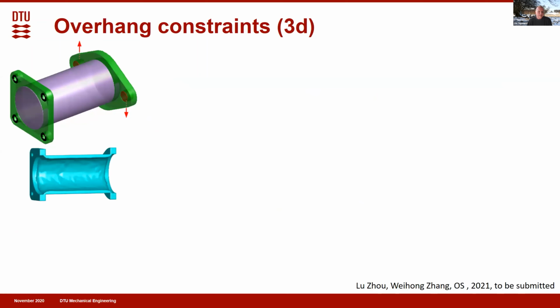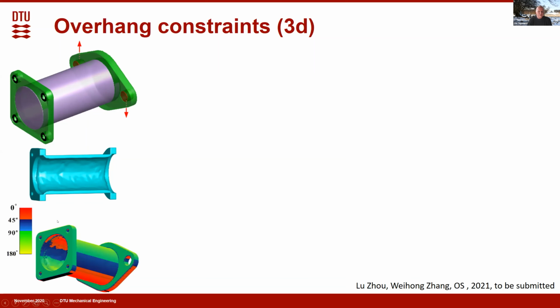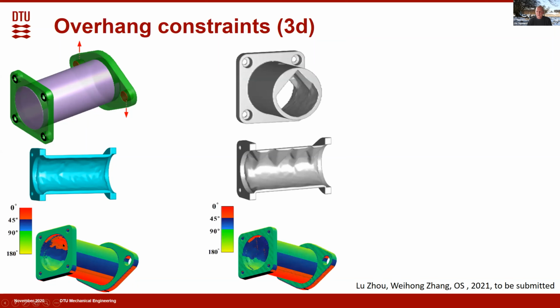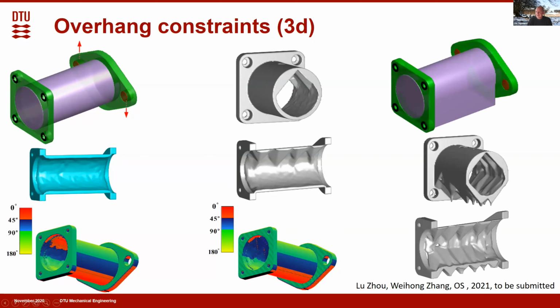Just shortly in 3D here, we had a torsion rod. So you have a support and a torsion load here. When we don't have any constraints, we would get a structure that's difficult to manufacture because it has overhang indicated by the red. If we introduce an overhang constraint, well, then the structure becomes like a droplet shape that never has less than 45-degree overhangs. You get sort of funny structures. Also, if you want to avoid external support structure, you can also introduce that and you get structures like this. So this was structural, but we could as well introduce this on the thermal or the fluid problems.